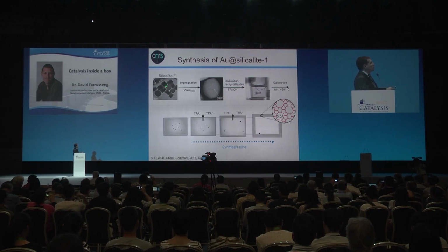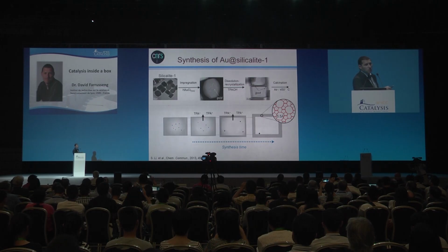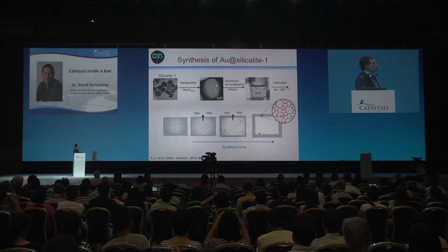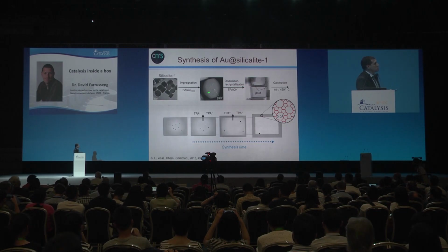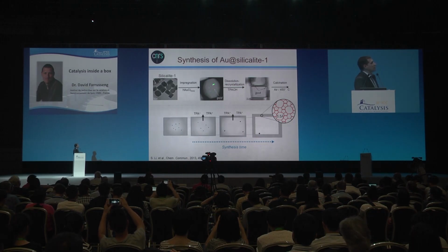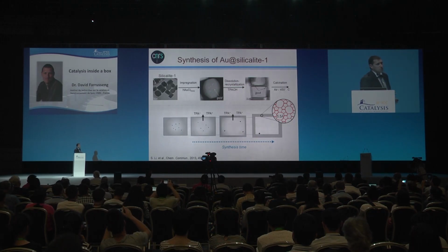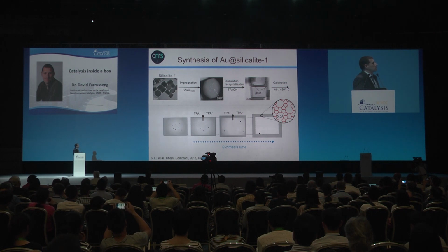So we start from silicalite-1, and we impregnate. In this case, we're going to do gold as the first example. We impregnate with gold solutions. After drying, we can see tiny particles inside the crystals where there is the maximum of defects.